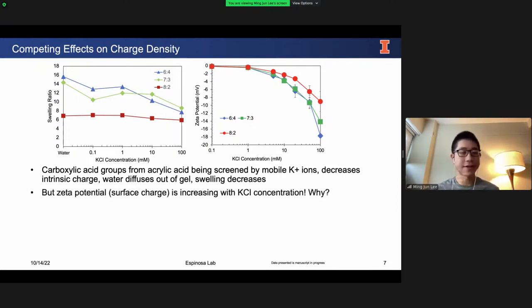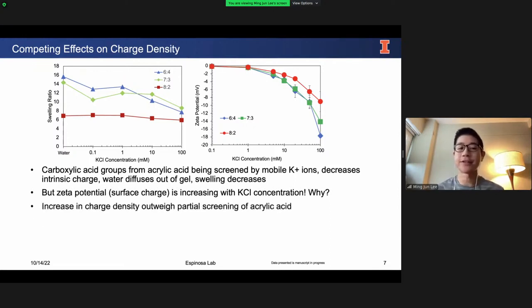But wait, I just said that the charges are being screened by the mobile ions. So why is the zeta potential getting stronger and stronger, more negative? This doesn't make sense. And I think that what's happening here is that there are actually competing effects between these phenomena. As the volume of the hydrogel is decreasing, what we're seeing is that the charge per unit volume, and therefore the charge per unit surface area of these hydrogels, is increasing. So the charge density is increasing, and that outweighs the partial screening of the acrylic acid, leading to the stronger zeta potentials that we see here.